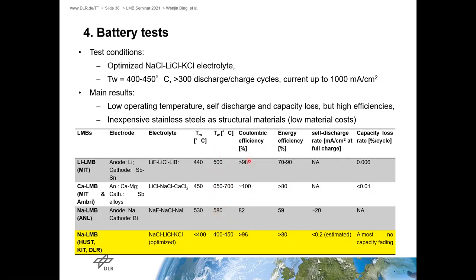And the efficiency here is higher than 96, and the energy efficiency is higher than 80. It's similar to the conventional batteries. The estimated self-discharge rate from the sodium solubility is also low, and the battery test also shows that the self-discharge has no problem. And one amazing result is that after 300 cycles, we can find almost no capacity fading.